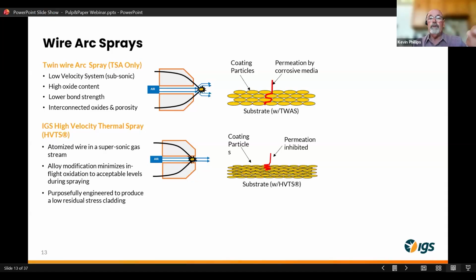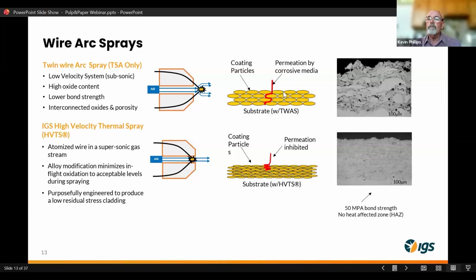So when you have an increase in oxide contents, a non-uniformity of your coating particulates, you end up with potential pathways. You have a potential pathway for your corrosive media to permeate through the coating into the substrate and attack the substrate, even though it has been cladded. And would result in obviously further degradation of the substrate, but also greatly affects the performance of the coating itself. When you have permeation, that kind of a coating is very subjected to disbondment or spalling.